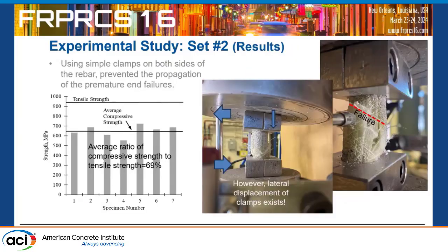So, here are the test results based on this one. We use just the one set of L over D. We reached a strength of 650 MPa. The tensile strength was around 1,000. So the capacity in compression over tension was 69%. So from 44% we reached 69%.